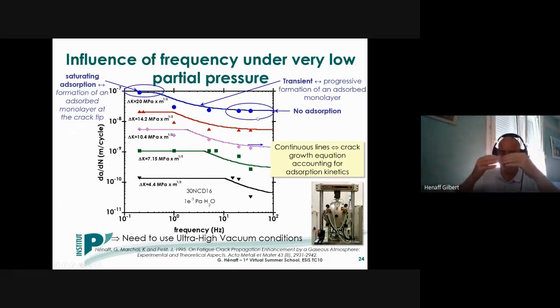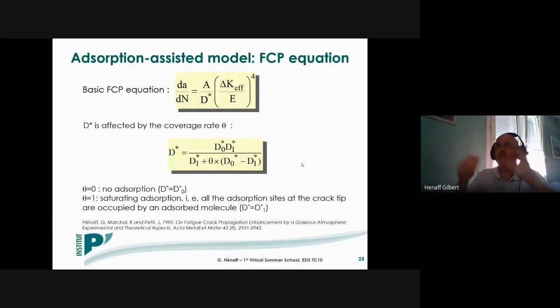At high frequency, it is assumed that due to the low water vapor pressure, the intrinsic crack growth rate is too high to form an adsorbed monolayer of water vapor molecules at the crack tip. As the frequency is progressively reduced, more and more water vapor molecules are adsorbed at the crack tip, and this enhances the crack growth rates. And finally, on this plateau, we assume that we have the formation of a uniform adsorbed monolayer at the crack tip. And the continuous lines on this graph are the results of an equation that has been established to account for the adsorption kinetics. And this is described here.